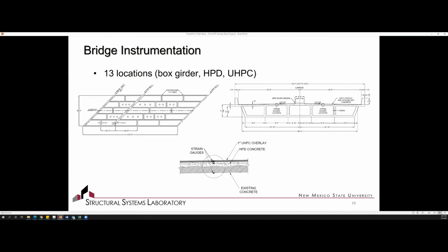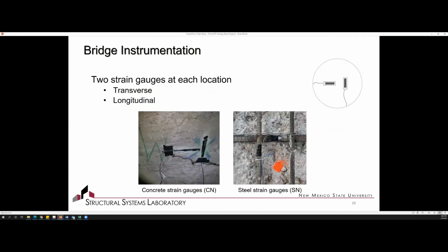And so the idea with these was that we wanted to do our best to get a vertical profile. So you can see down here, we're trying to align the strain gauges along the cross section, so we get a strain distribution along those three different materials: the existing concrete of the box girders, the HPD concrete that was just cast, and then the UHPC overlay, so we could look at the strain profiles in the materials. We put 2 strain gauges at each location, so we're looking at both transverse and longitudinal behavior. So you can see there we have the concrete gauges on the interior, and then we have the steel strain gauges that were embedded into the HPD layer.